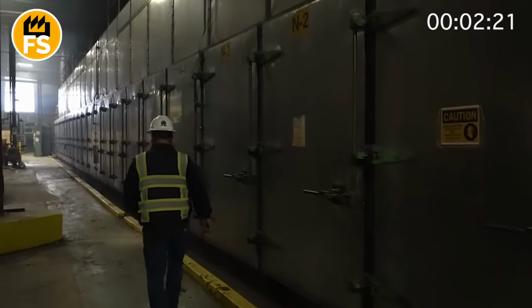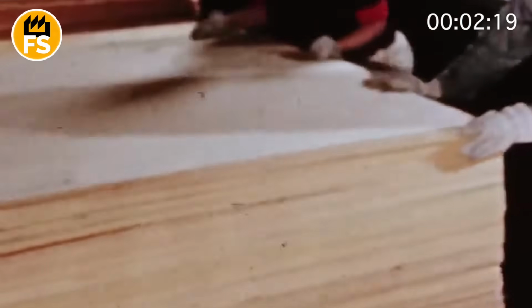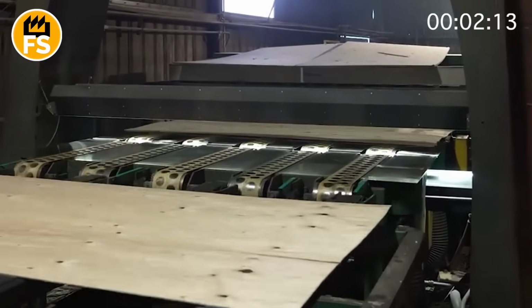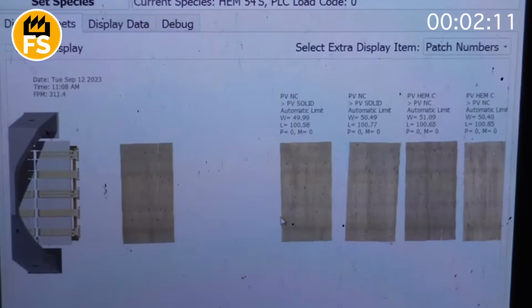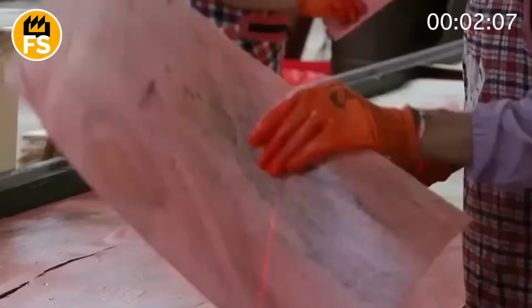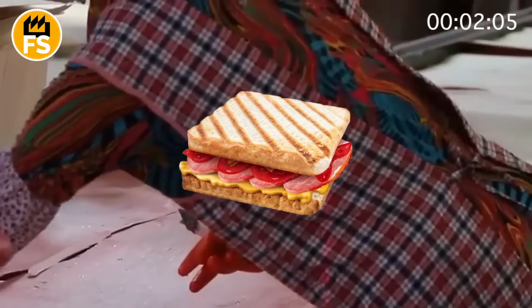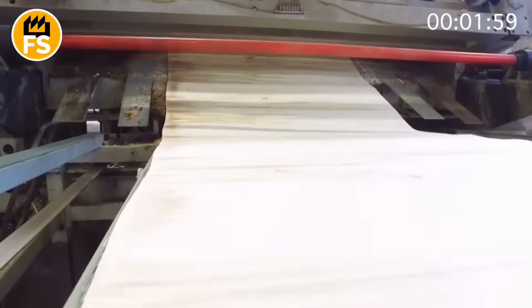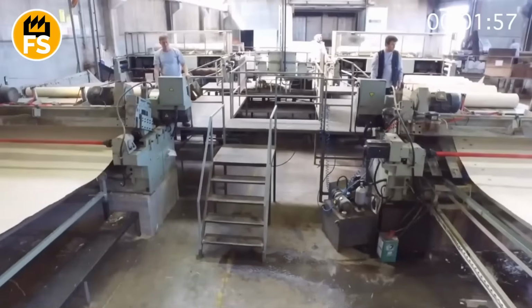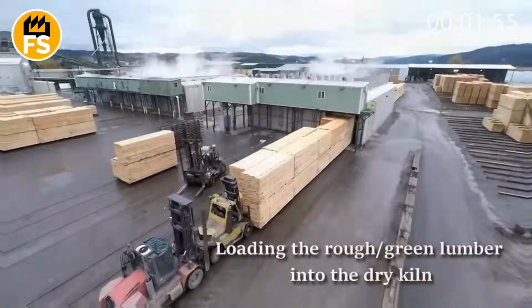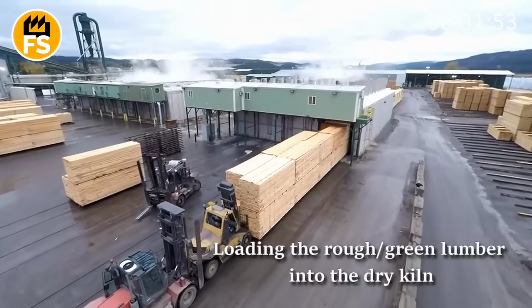Because plywood isn't just glued sheets, it's cross-laminated layers, where each layer runs perpendicular to the previous one. This is how it gets its mechanical strength, flexibility, and resistance to warping, like a bulletproof vest, but made of wood. The finished sandwiches of several layers are placed in a giant hydraulic press that applies pressure from 150 to 250 psi at a temperature of about 300 degrees Fahrenheit.